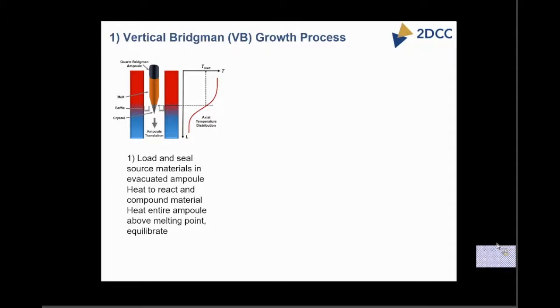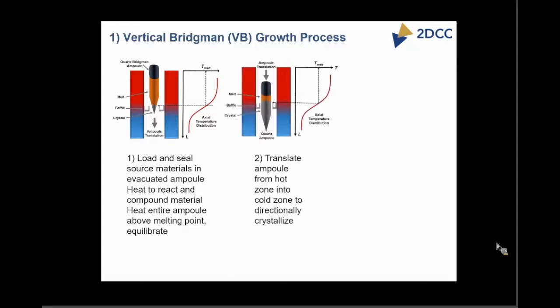We're actually adding a rocking furnace that will be used for compounding materials, particularly where there's a high exothermic heat of reaction. Once you have the material in a compound form, heated above the melting point, allow it to equilibrate, and then translate it through this temperature gradient. So through the melting point region, which you often can establish in a furnace through the zone configuration, internal baffling, etc. So there's some engineering that goes into designing these to get the gradients right, maximize the gradient, optimize the gradient without creating excessive stresses in the material.